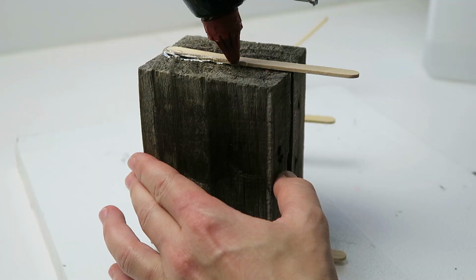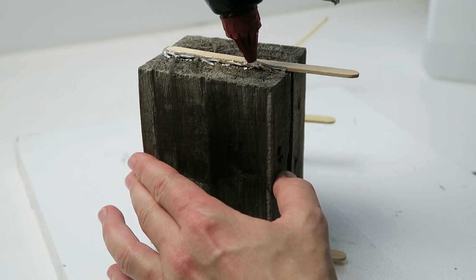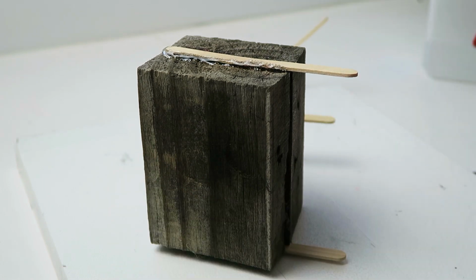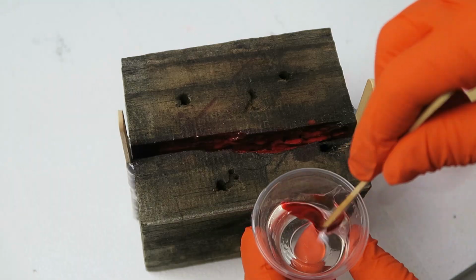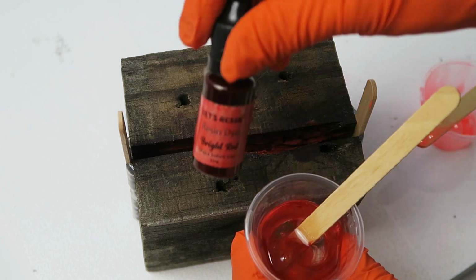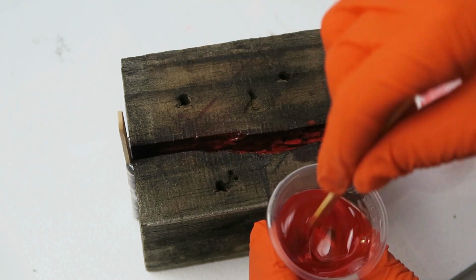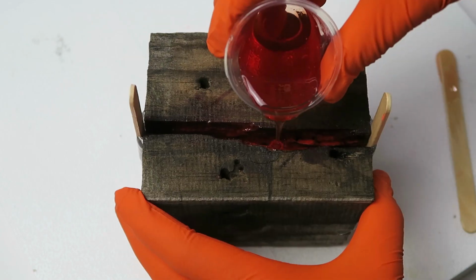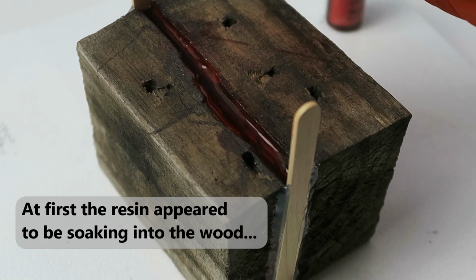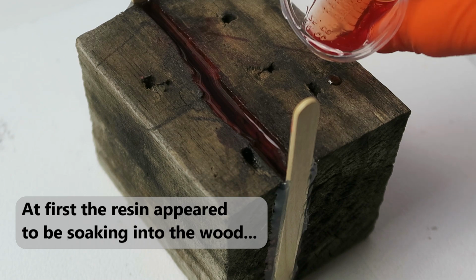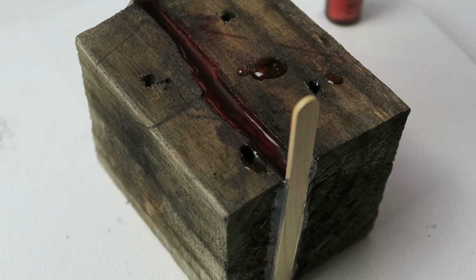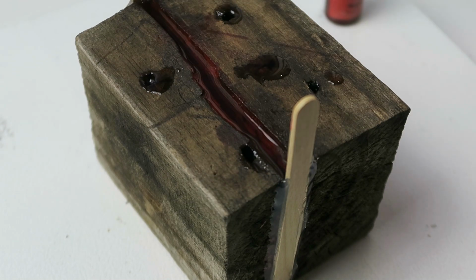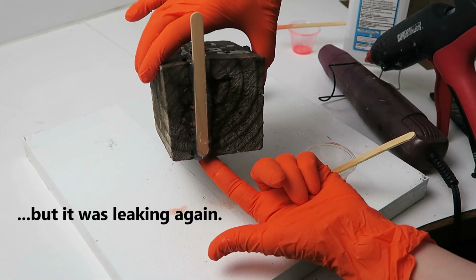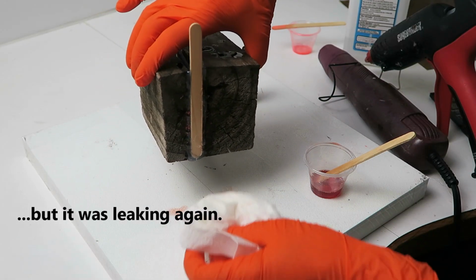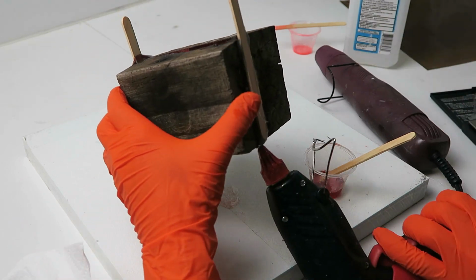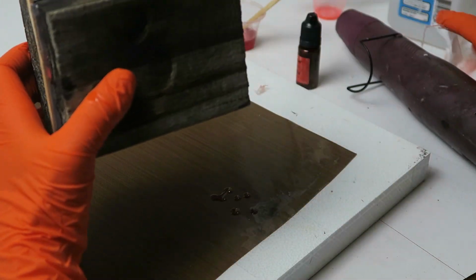After removing the gum tape and wiping up the resin drips, I instead closed up the sides with hot glue and craft sticks and poured in a new batch of resin. It seemed to be working, but actually, it was just leaking more slowly through small cracks at the bottom that I thought had been sealed with the first resin application, but apparently not. So I kept adding hot glue until the resin stopped escaping.